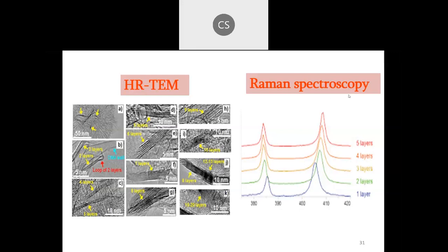So this is a Raman spectrum of the same material, from a single layer to 5 layers. You can see how these Raman bands vary, and as the layer number is increased, the band positions keep on shifting to both the left side as well as the right side. So the distance between these two Raman peaks gives you an idea about the layer number of the 2D materials. So for the faculty who are interested to analyze 2D materials, Raman is the most powerful and easily available characterization technique, and we can easily analyze the layer number through Raman spectrum methods.